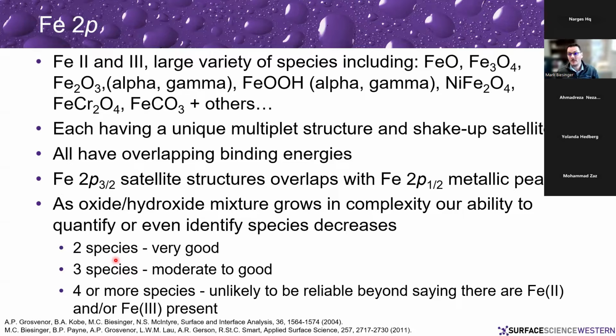Iron is probably the worst of them all for curve fitting. You can have iron 2 and iron 3 species. You get a large variety. You've got FeO, Fe3O4, Fe2O3, both alpha and gamma phases, FeOOH, alpha and gamma and other phases, things like nickel ferrites, chromites, carbonates, sulfates, et cetera, et cetera. Each will have a unique multiplet structure and shake-up satellites. They're all going to have overlapping binding energies. They're all just iron 2 and iron 3, so they're not shifting a huge amount.